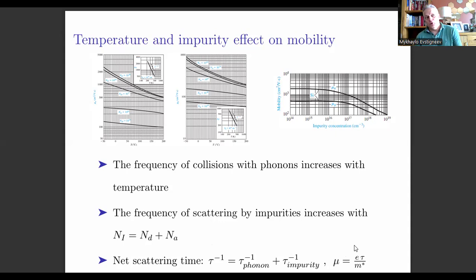in a unit volume. So the concentration of donors plus the concentration of acceptors. And it also should be proportional to the temperature raised to some power. So it is not a direct proportionality. The frequency of collisions increases with temperature, but not as the first power of temperature. In silicon, empirically, we know that the frequency of collisions increases with temperature as T to the power 2.2 or 2.3, depending on what kind of charge carriers these are, electrons or holes.